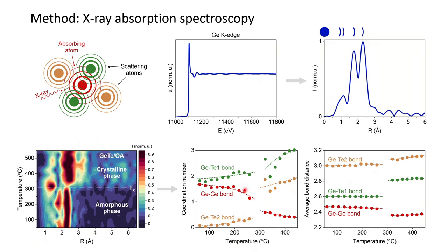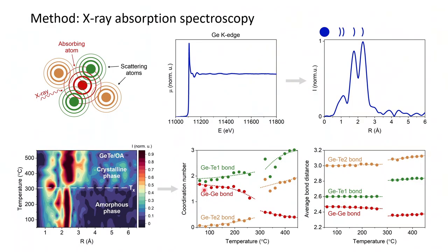Let's focus a little bit on the amorphous side. This is this region. So it looks like, two conclusions from that plot. It looks like the amorphous structure is not really very linked. So it has a relatively low coordination number for the nearest tellurium bond, which one can intuitively guess because it's amorphous. And another interesting feature is that the amorphous structure has a lot of germanium-germanium bonds.